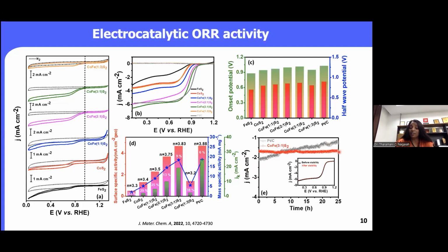After the chronoamperometric studies, again, we have performed the hydrodynamic condition, and you can see that the LSV curve displays that there is no decay either in the onset potential or in the diffusion limited current. This demonstrates that our catalyst is quite stable. So that means the cobalt iron with the 3:1 ratio is good towards the HER as well as ORR as well.